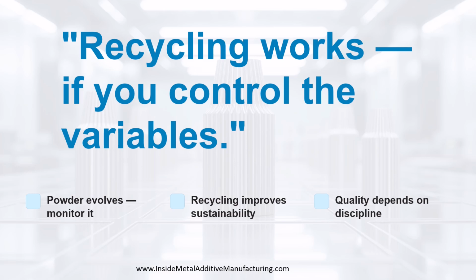So what's the big picture? Powder recycling isn't inherently good or bad. It's a materials evolution process, one that must be measured, controlled, and understood. If we manage oxygen levels, maintain effective sieving, track PSD shifts, and pay attention to flowability and powder bed density, then recycled powder can be used sustainably, safely, and without compromising part performance. And that's the real story behind powder recycling in LPBF.